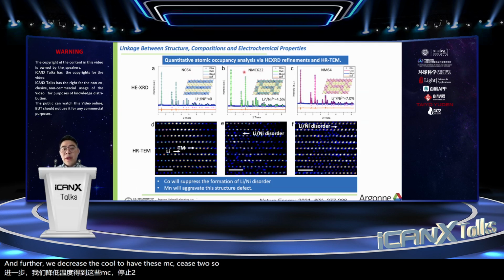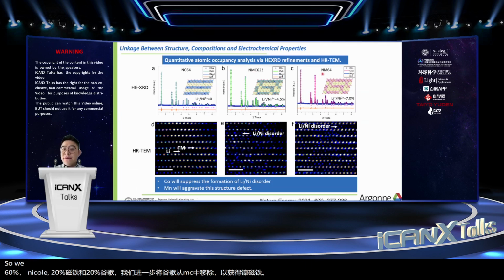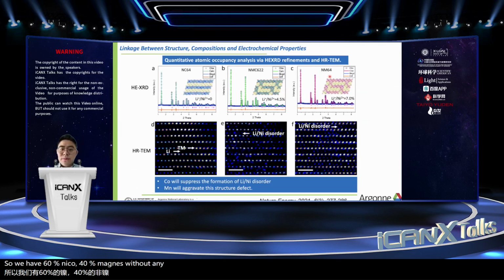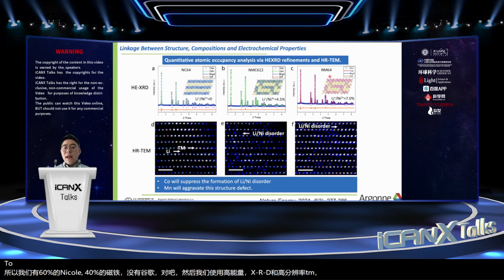So that means we have 60% nickel, 20% manganese, and 20% cobalt. We further remove cobalt from the NMC to have the nickel manganese 64. So we have 60% nickel, 40% manganese without any cobalt, right? And then we use high energy XRD and high resolution TEM to analyze the fine structure.